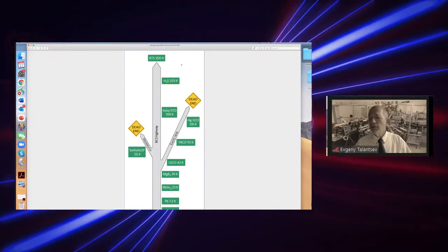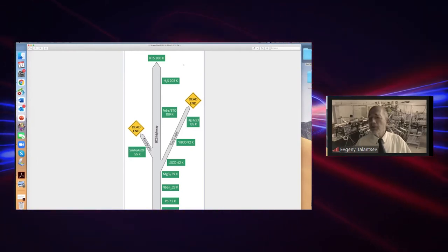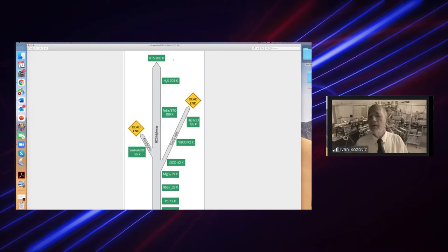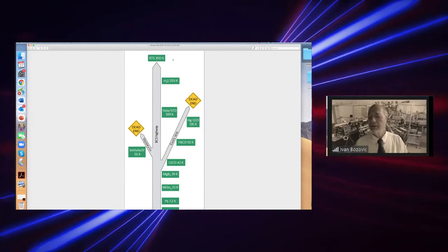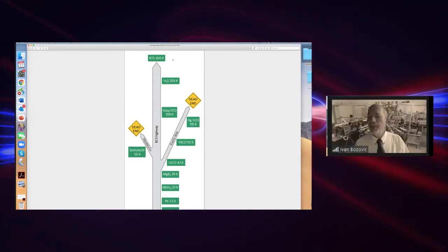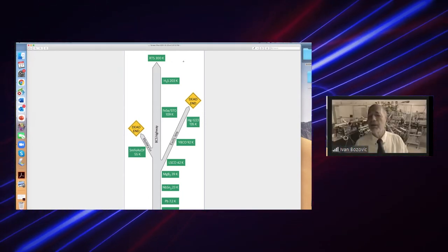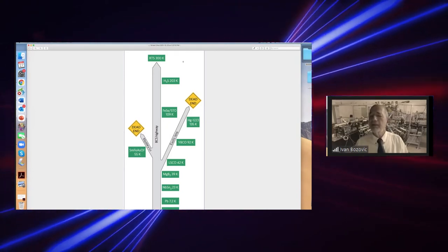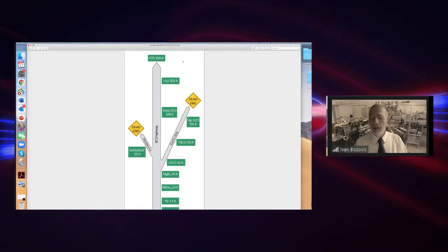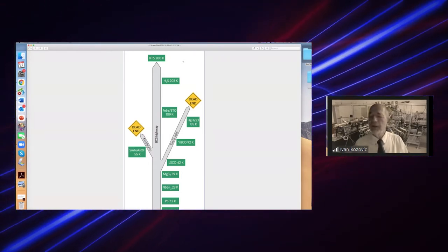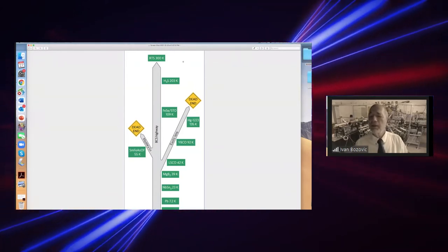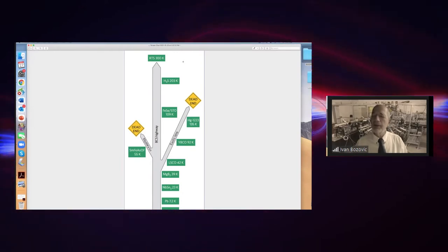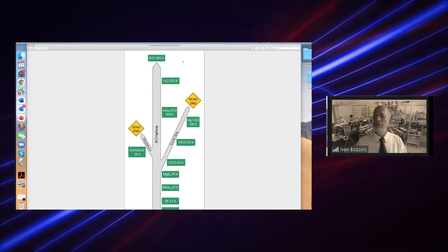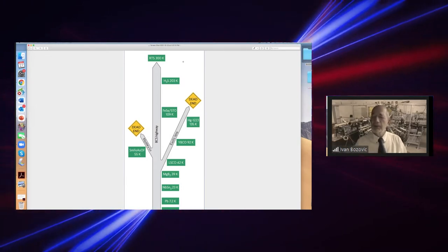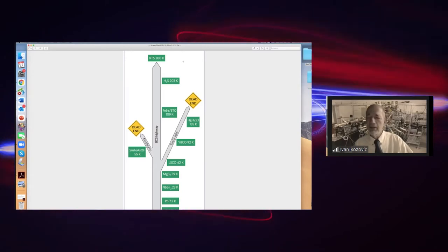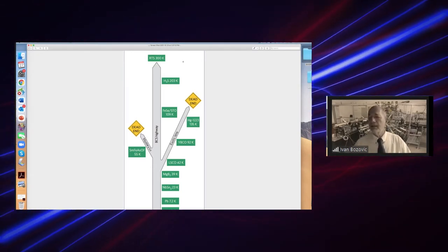Yeah, it was measured about 1 month ago. They did it. Yes, that group. You have to read the paper carefully. I have read that paper. It's posted on the cond-mat. And if you look at the data, they see a drop in zero field. But when it is field cooled, there is nothing there. So you see screening, but there is no Meissner effect. Meissner effect is flux expulsion. So when you cool it in field, below the critical field, it should expel the magnetic field, and that's not seen. So I don't understand what's going on in hydrides.